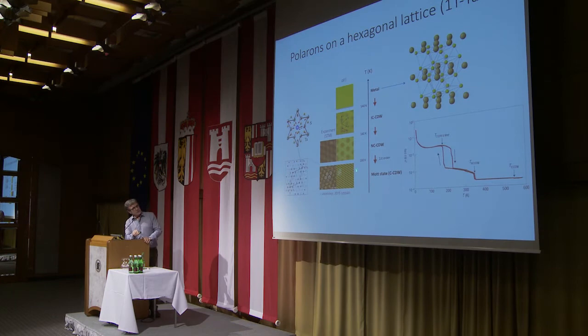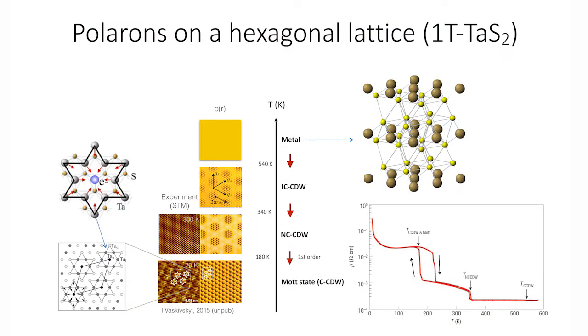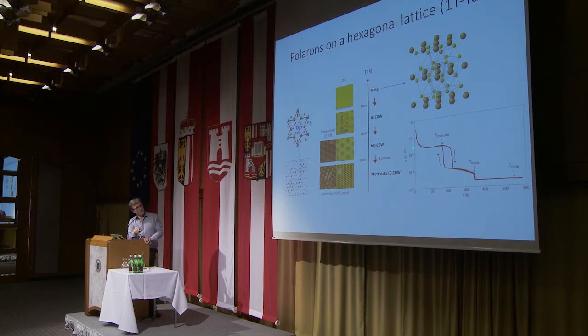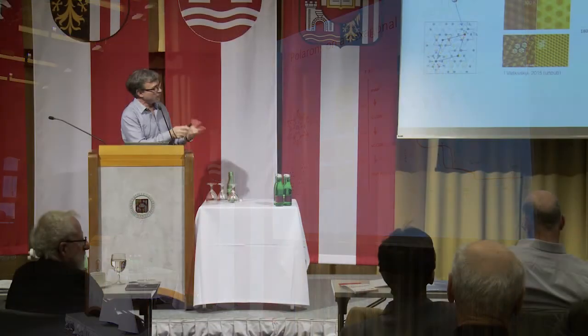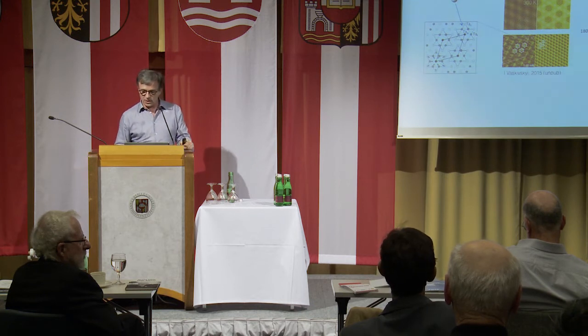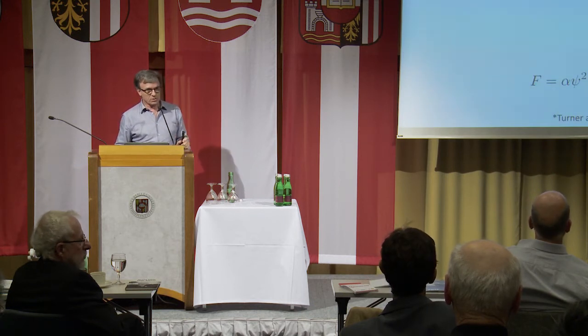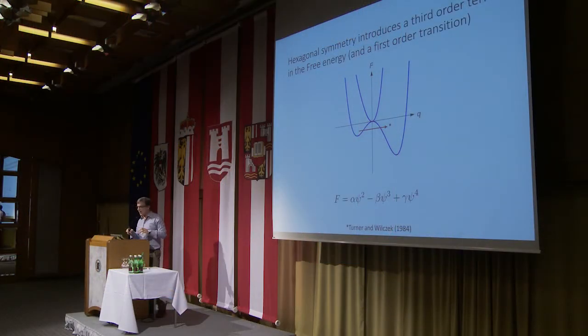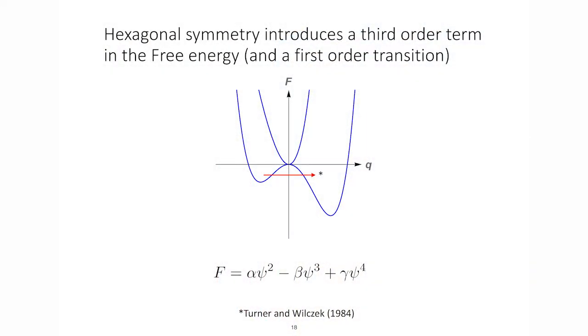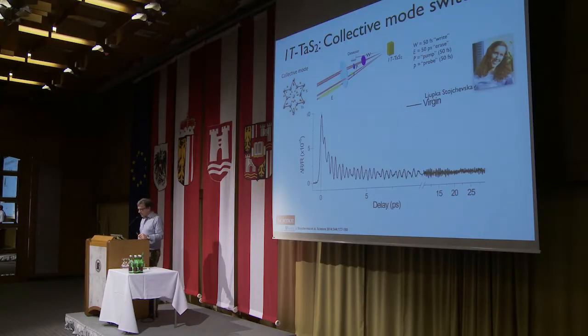So essentially, this is the lattice that you have, okay? And as you go through these transitions, the resistivity shows nice jumps, basically going to an insulating state at low temperature. And what we're going to do is start with this low temperature state and try and change it somehow with our experiment. Just a note for consistency, it's the hexagonal structure which allows us to have a third order term in the free energy, if there are some theorists around here, and that basically gives you a metastable state. Okay, so how do we do this?